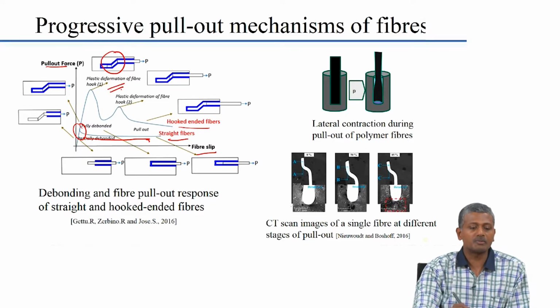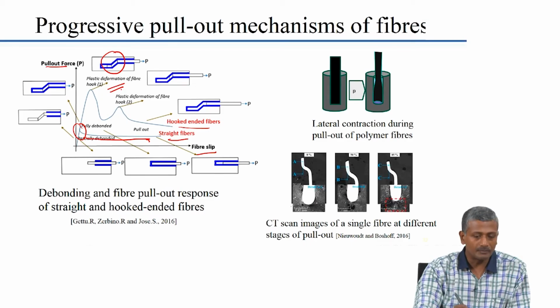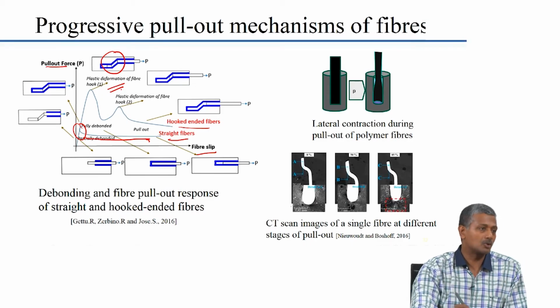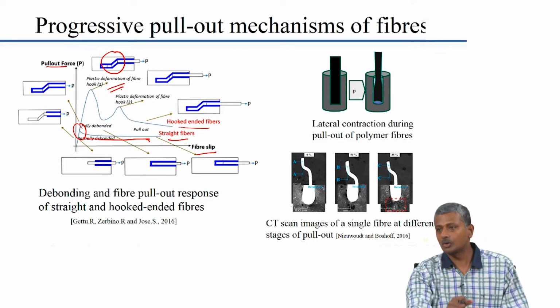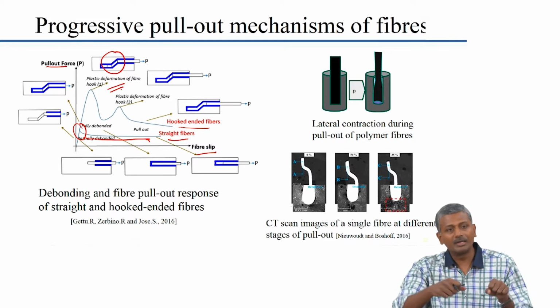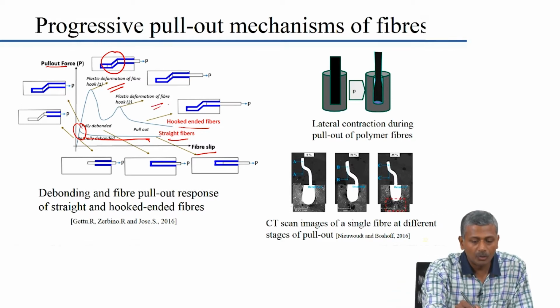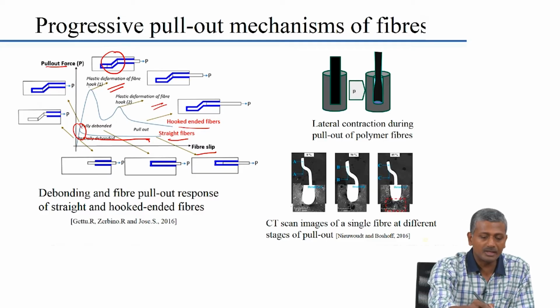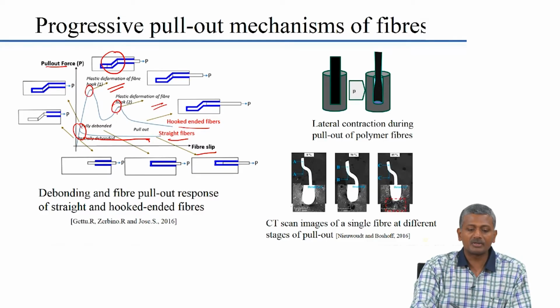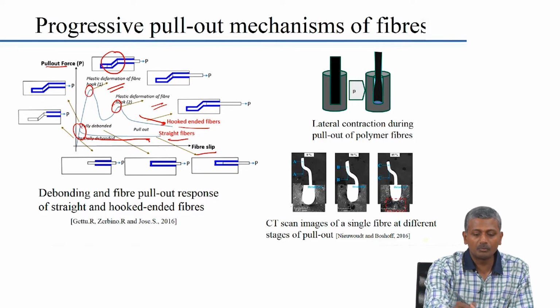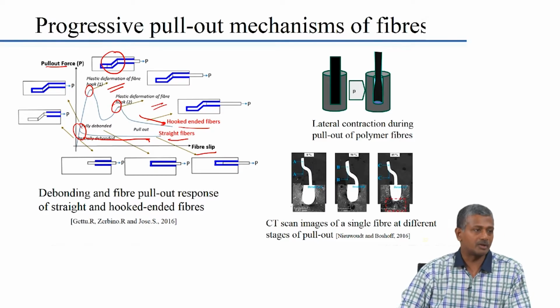So, here what you see because of this increase in load is because of the plastic deformation of the hook itself. Again, this hook first starts straightening out and then only it starts getting pulled out. So, this plastic deformation actually leads to these humps being formed in this diagram, and finally there is pull out that is actually happening with the hooked end steel fibers.